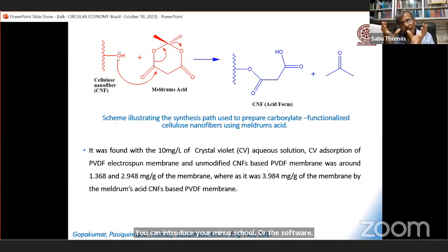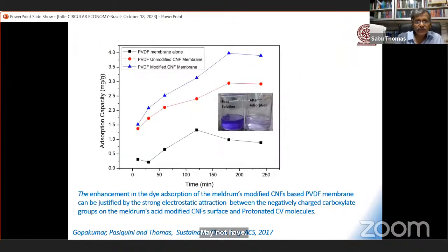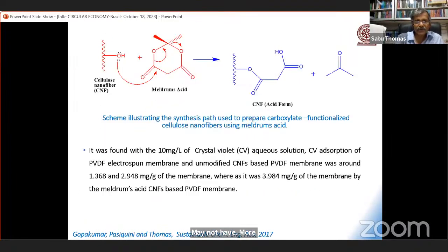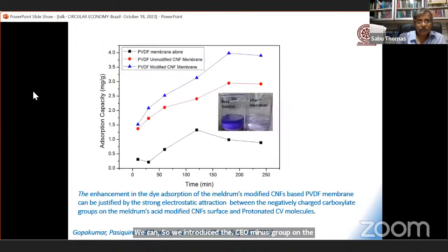The idea is to put more CO minus groups and make nanocellulose electronegative. That is the purpose of putting the CO minus group on the surface of nanocellulose. This is a clean chemistry, green chemistry. So we introduced the CO minus group on the surface of nanocellulose. Now I'm going to show you the results we got.